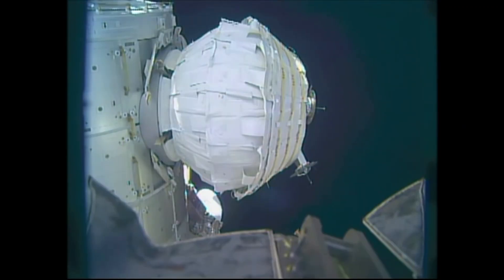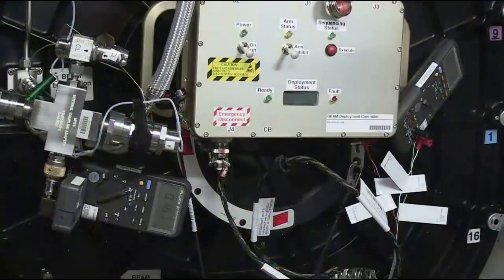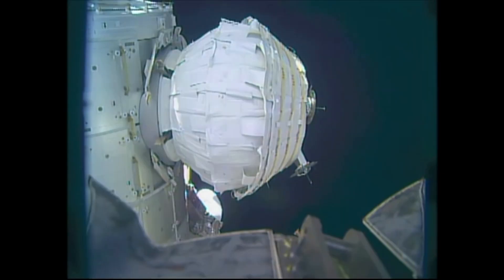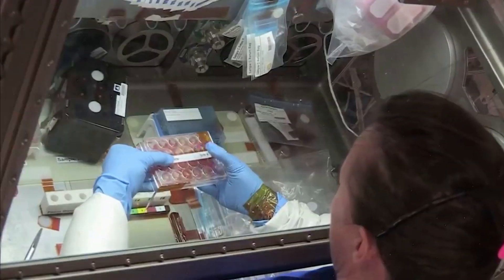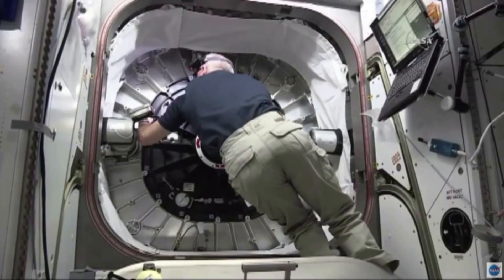While overall it performed much better than expected, it did have a few problems at the beginning. The first attempt at module inflation took place in 2016 and was suspended after higher than expected air pressure inside BEAM was detected with minimal expansion of the module. The attempt was terminated after two hours. The failure to expand and unfold may have been the result of the unanticipated 10-month delay in module inflation, which may have caused the fabric layers to stick together. Eventually, the module was expanded over the course of 7 hours, with air being injected 25 times for a total of 2 minutes and 27 seconds. After expansion was complete, air tanks aboard BEAM were opened to equalize air pressure in the module with that of the ISS.